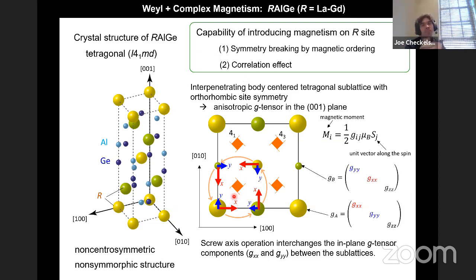So the idea is that the system has a set of 4-1 screw axes, which, if you look in the tetragonal plane, sit at these points. And so I've colored this rare earth atom in 2 different colors. It's the same atom, but what I'm trying to show you is the atom before and after this symmetry operation. And what's interesting about this system, and this is really getting into the weeds, is that the site symmetry for each of these atoms is orthorhombic. So it's actually the local XY axes are allowed to be different in this crystal.